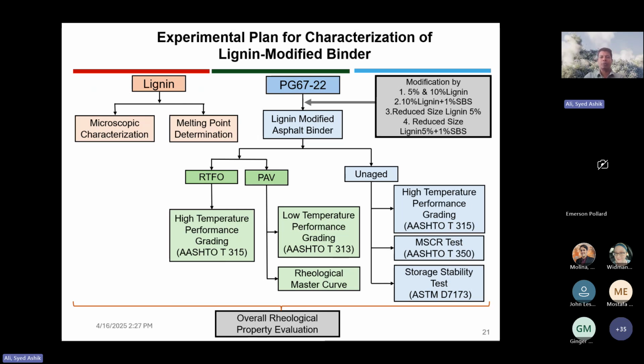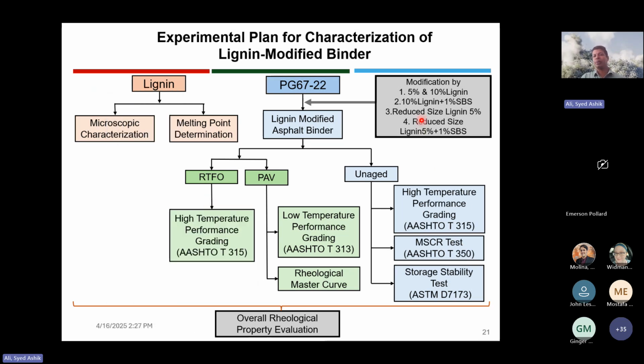So at the same time, when we were doing the 5% and 10% modification, we also did some other things as well. We did a 10% lignin modification with 1% styrene butadiene styrene or SBS modification. We also prepared another modified binder with reduced size lignin at 5%, and also another modified binder with reduced size 5% lignin with 1% styrene butadiene styrene. The purpose of using styrene butadiene styrene and also the reduced size lignin, as Dr. Lynam was explaining how we got that reduced size lignin, was to see whether we can use those products to improve the storage stability of lignin modified asphalt binder.